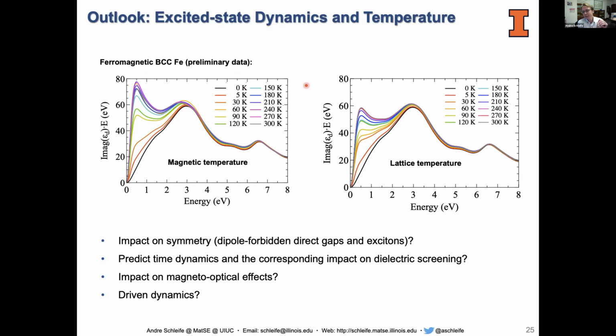Keesong found an interesting effect here in ferromagnetic iron, where both a lattice temperature, in other words phonons, and a magnetic temperature going away from zero really change your dielectric function, or in other words, the optical properties of the material. The contribution you see here is without the Drude model, which may matter for iron, but the effect is a strong influence on this dielectric function through magnetic temperature as well as lattice temperature. And I think that is really a promising direction to study.